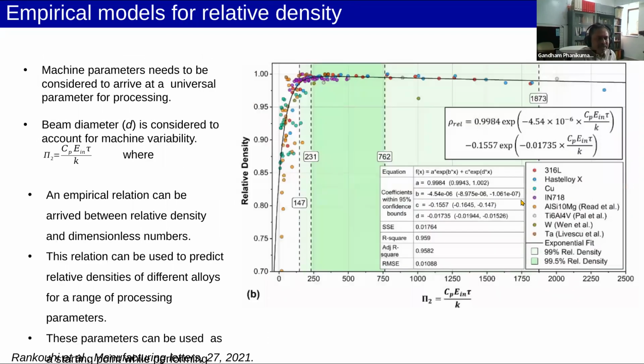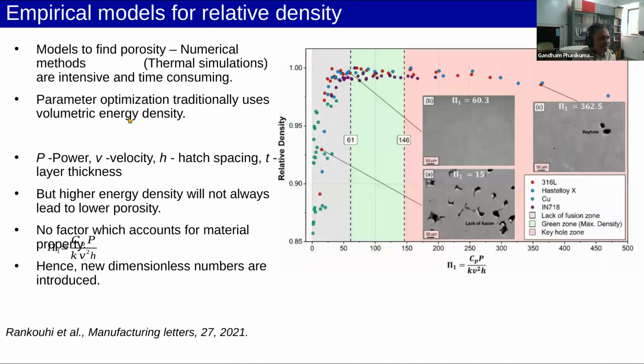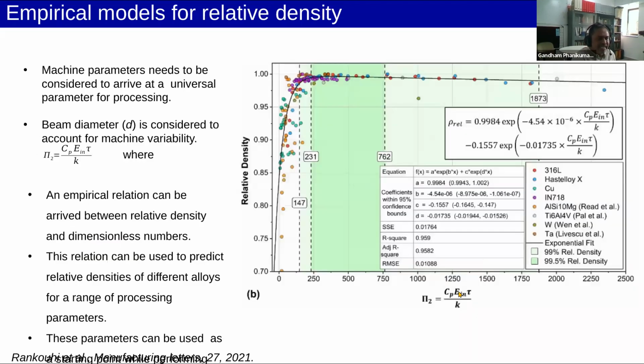Okay, and that empirical correlation is given here, and it does take into account the energy input to the powder, E_in. The E_in itself is defined here. While making the PDF it has gone behind the text, but it is basically a combination of the parameters: power, velocity, hatch spacing, and layer thickness. Power divided by the three quantities: velocity, hatch spacing, and layer thickness. And that E is going into the calculations, which is a good idea since it takes into account some of the physics. So these can be used to eliminate porosity formation as a first cut.